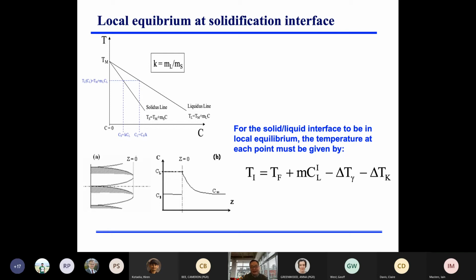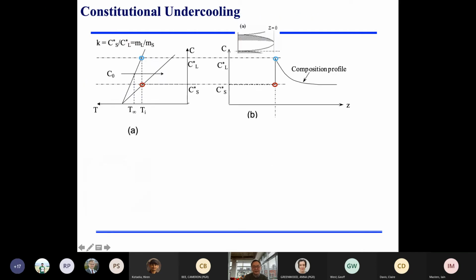And also, this means the interface temperature is pretty much fixed. Looking at this interface temperature, we can start with Tm, and then the distance between those two is essentially the slope times the concentration difference, and take away those two terms. The first term is curvature. The curvature always plays a role, in particular when looking at the Gibbs-Thomson effect, and it's important. And delta TK is kinetic, and normally you can ignore it, it's probably 1 or 2 orders of magnitude lower than those two, and this is also probably 1 or 2 orders of magnitude lower than this undercooling.